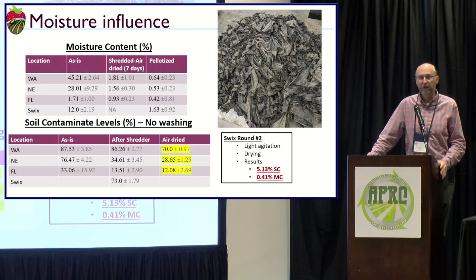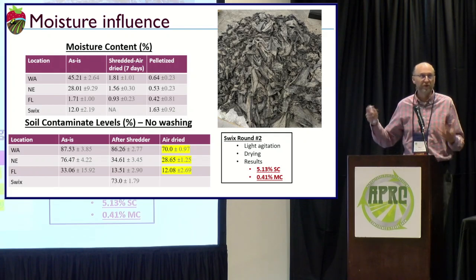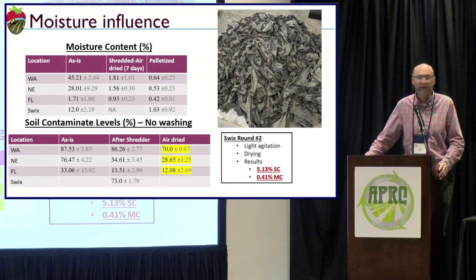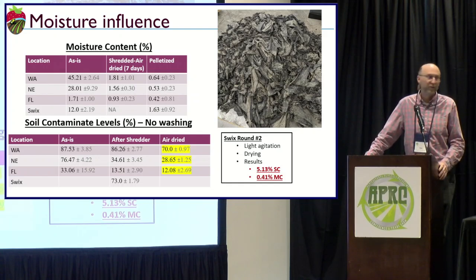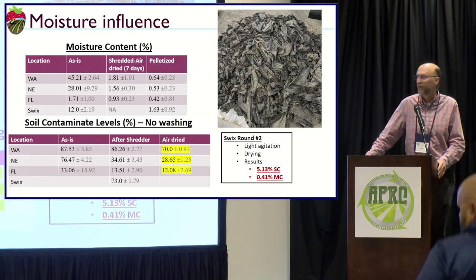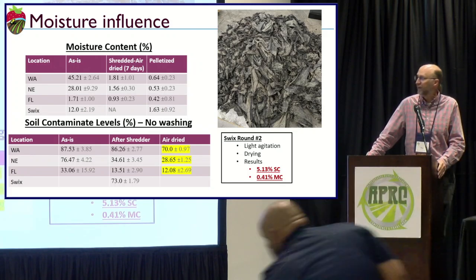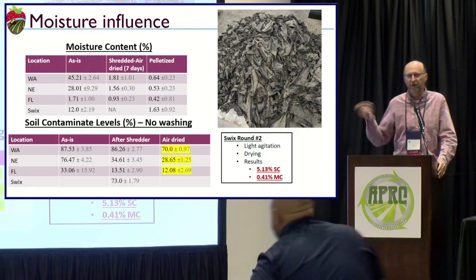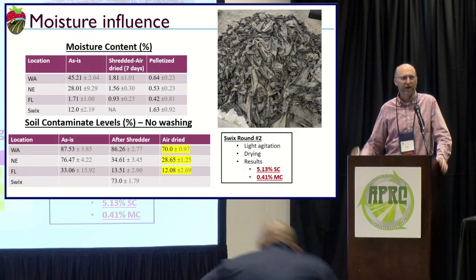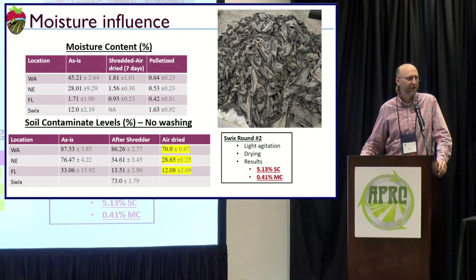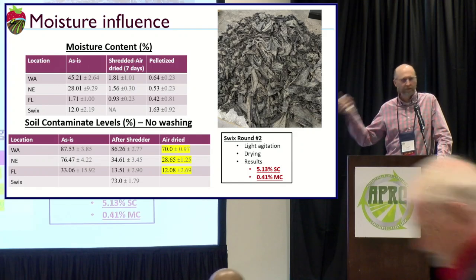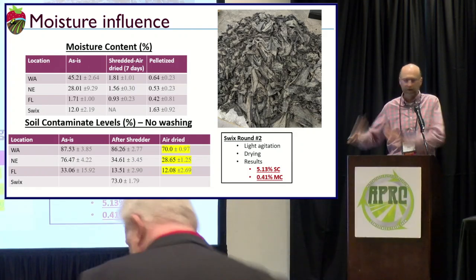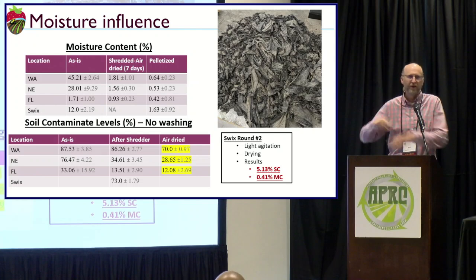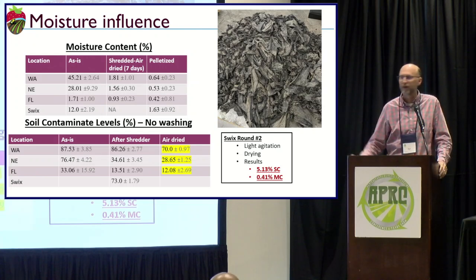Same thing with the Swix material. It came in shredded for us because it was so much material, and we wanted to have it shredded before we got it. It came in at what Gene was basically saying, 70, 80%. We got about 73%, so our data lines up pretty well with what Gene is getting. But we just did the second bale. When we did the first run of the Swix material, we just took it right out of the bale and made pellets out of it, so it had that high contaminant level.